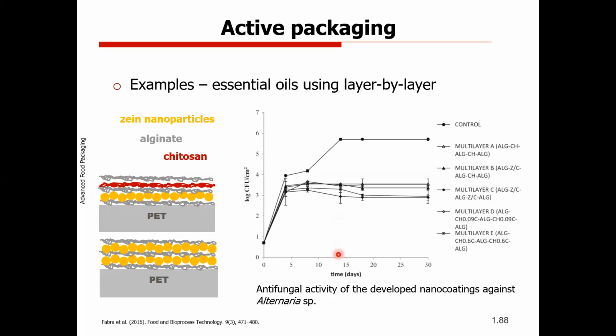In this case, we try this against fungus. In this case, Alternaria. And we saw that we are able to reduce the growth if you are using this system. That is interesting because you are using a very low amount of essential oil. You are working at nanoscale, and you are able to protect this capability during several days. So you can see that after 30 days, you still have this activity, such as in day 5.